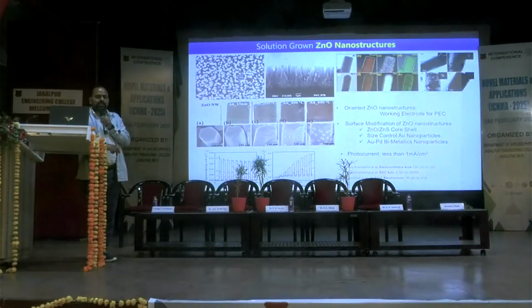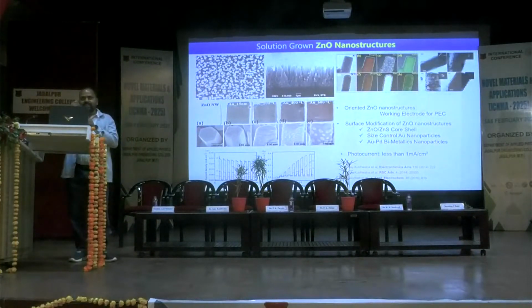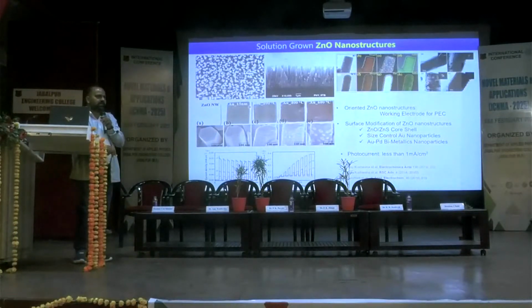If you look at the industrial requirement, it should be roughly more than 10 milliampere per centimeter square if you would like to think about industrial application. So it's still very, very less. And of course, stability was another issue. Though it's a metal oxide system, it's still not very stable. After a couple of hours, it gets degraded.